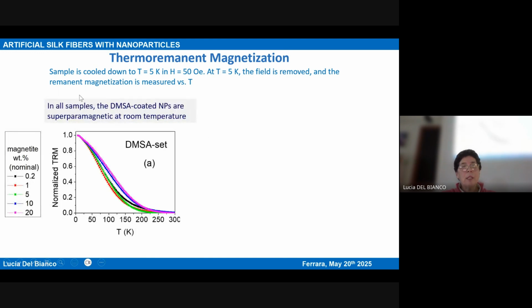For instance, in the case of the DMSA coated nanoparticles, this is what we observed. In this case, all the curves are normalized to the initial remanence value, but what you observe is that the remanence is decreasing. And it's decreasing because with increasing temperature, more and more nanoparticles enter into the superparamagnetic regime. And at room temperature, 300 Kelvin, your remanence is completely annihilated, which means that all the nanoparticles have entered into the superparamagnetic regime.